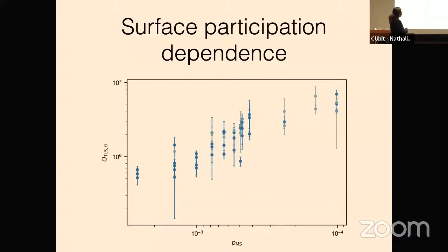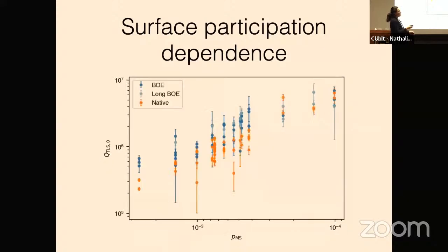But as you make the devices bigger, they get better. So you get this quality factor scaling that goes up. But then interestingly, for the largest devices, everything kind of plateaus. So you have something that's creeping in here that is no longer surface dependent. And then we can do things like compare two different surfaces that you prepare with chemical processing. So these are our native oxide samples, and then we can do a really standard trick in silicon processing, which is dip the whole thing in buffered oxide etch to try to pull off a little bit of the oxide.